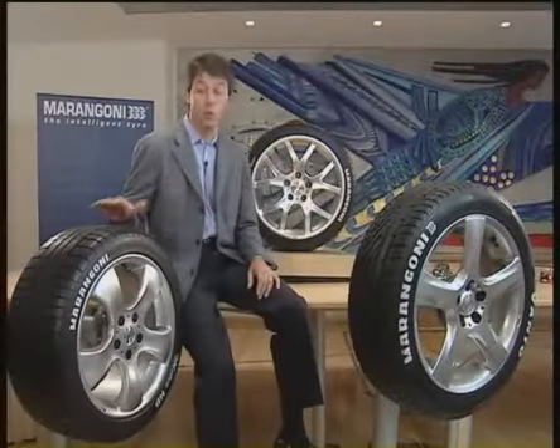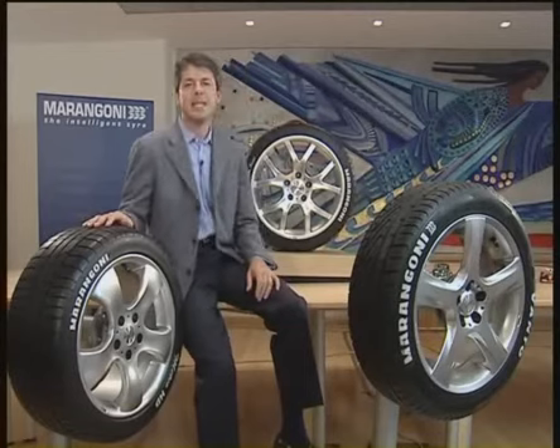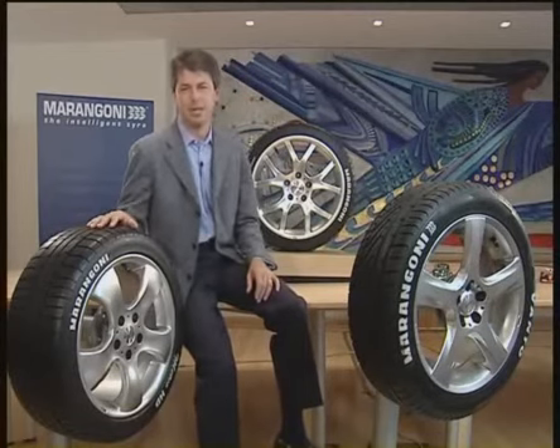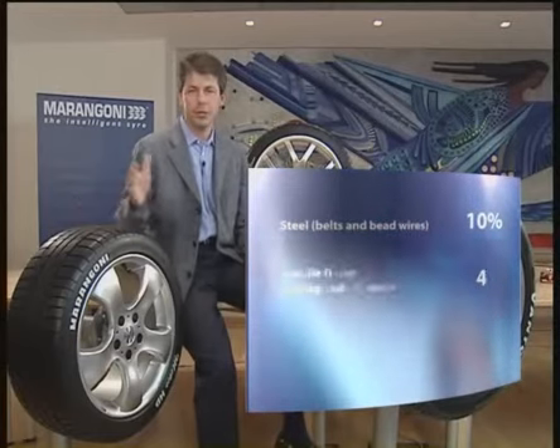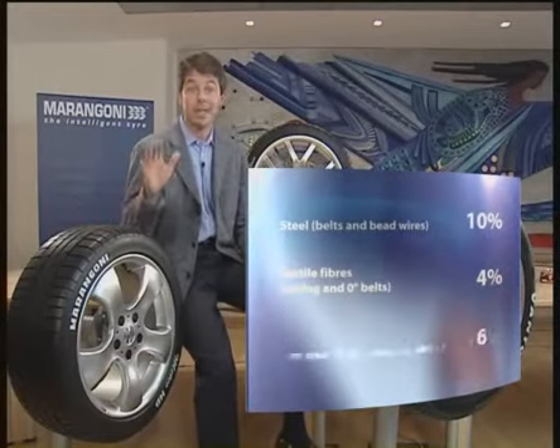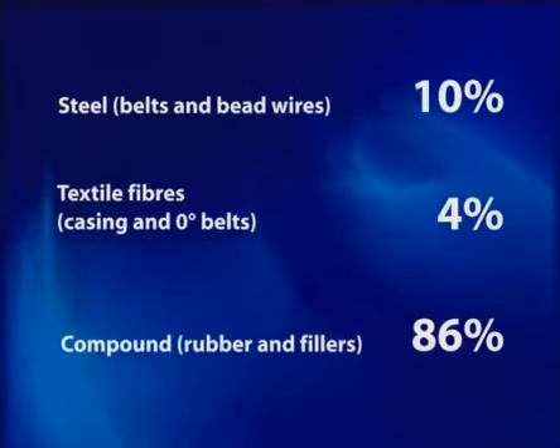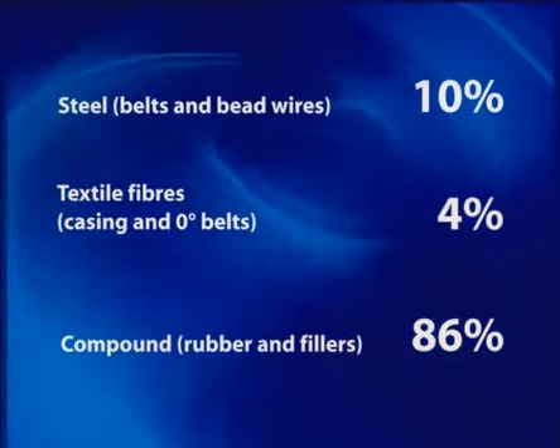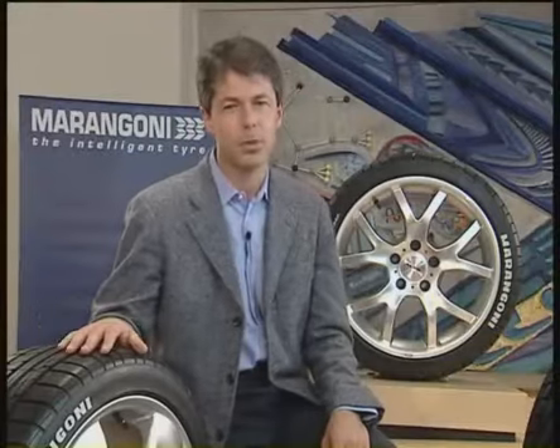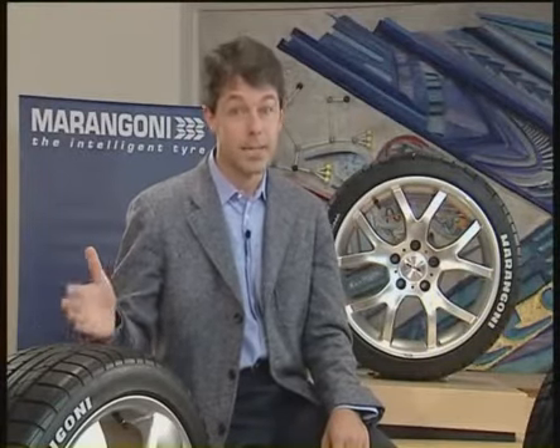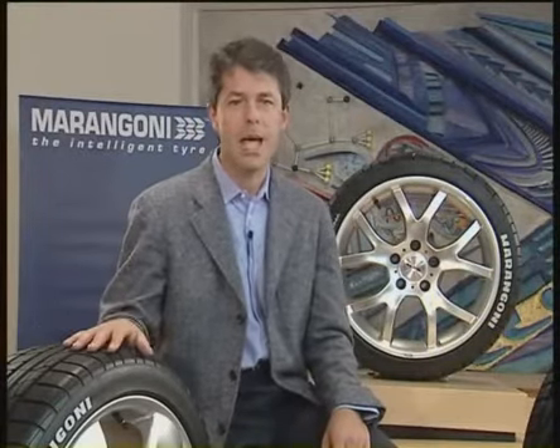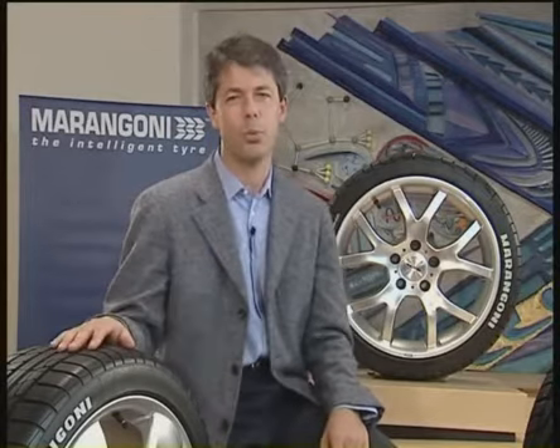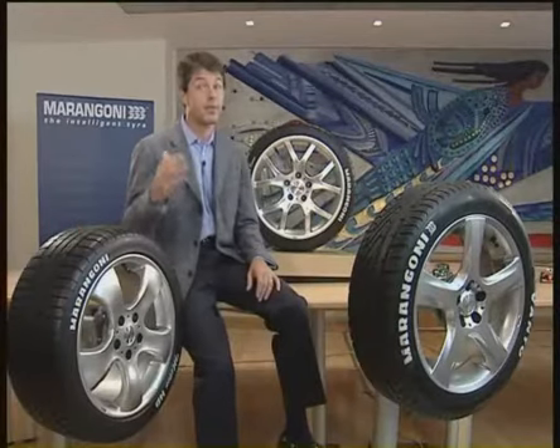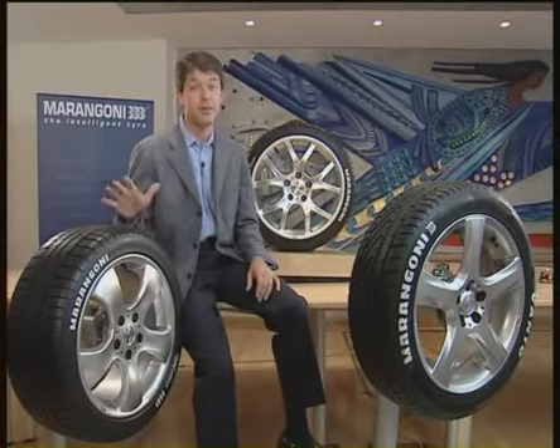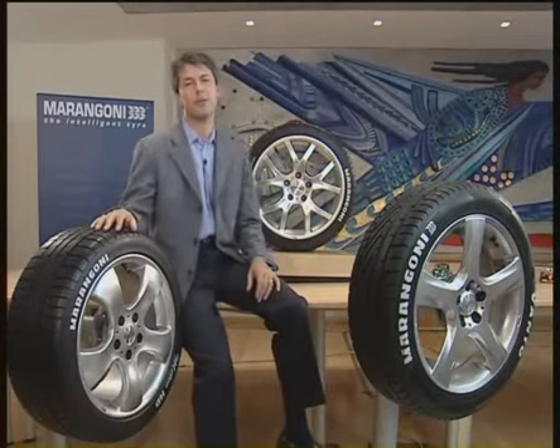Thus, a tire contains three different types of materials present in different percentages: 10% steel, 4% textile fibers, and the remaining 86% compounds. In turn, the compounds, that is, natural or synthetic rubber, with the addition of various chemical products, may be present in up to 12 different formulations in the same tire. Combining such different materials while at the same time ensuring functional efficiency is a real technological challenge.